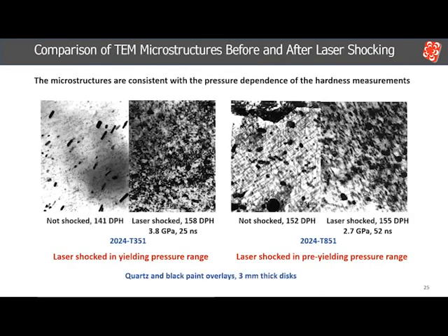Here we see transmission electron micrographs of two of the specimens laser shocked in the previous slide. The work-hardened 2024 T351 shows a large increase in dislocation density after laser shocking. The hardness was about 158 DPH, well above the unshocked hardness of 140 DPH. However, the stronger 2024 T851 on the right shows very little increase in dislocation density. Laser shocking was unable to overcome the resistance to deformation contributed by precipitation hardening from the thin, semi-coherent, lath-like S' precipitates below 2.7 GPa.